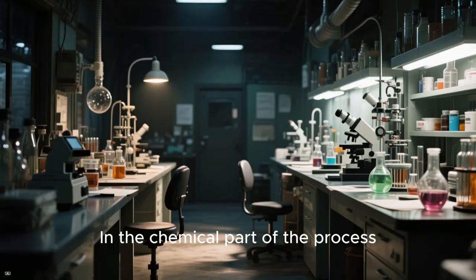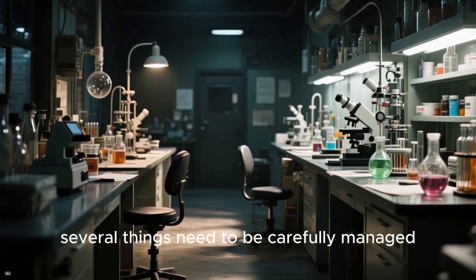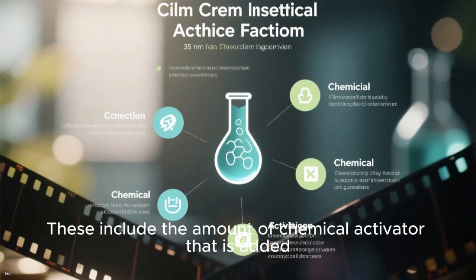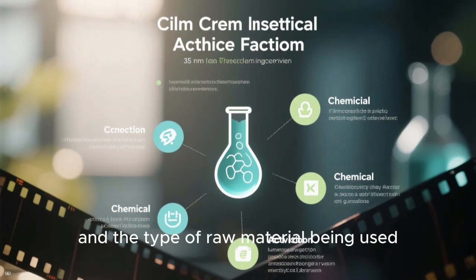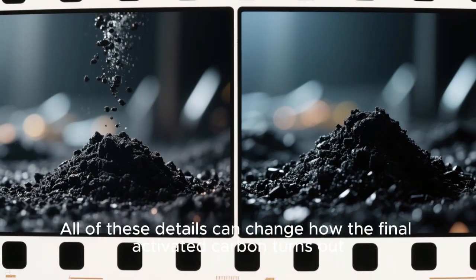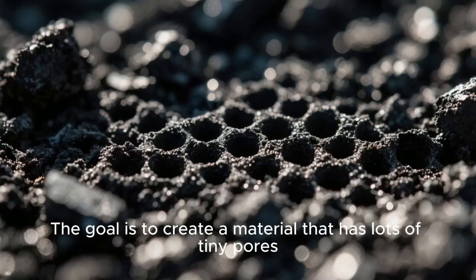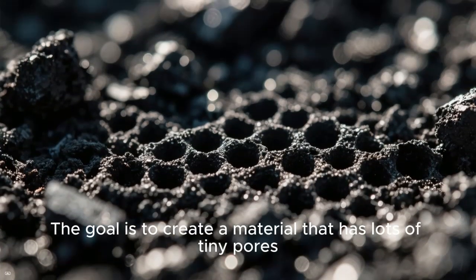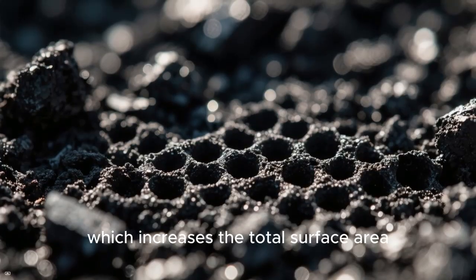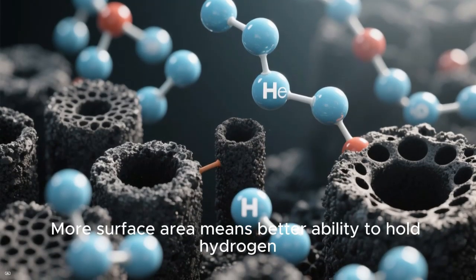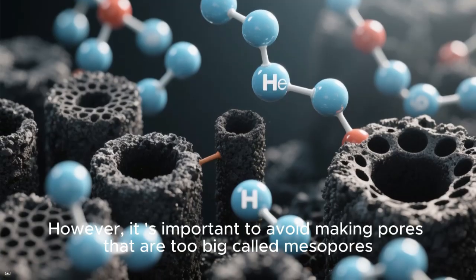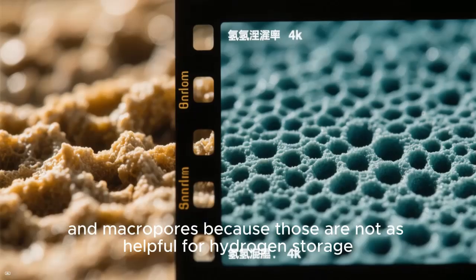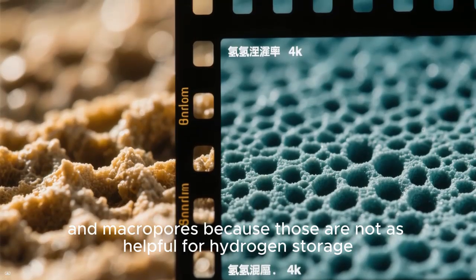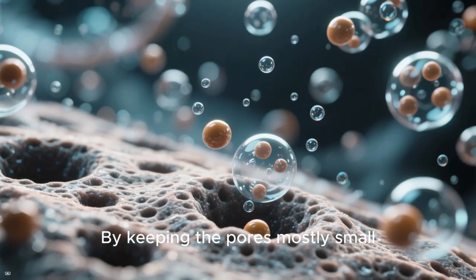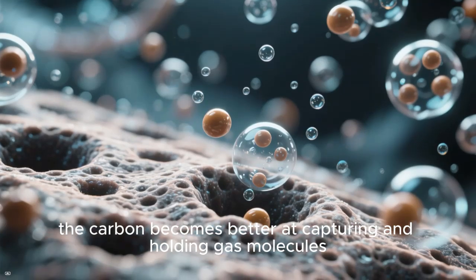In the chemical part of the process, several things need to be carefully managed. These include the amount of chemical activator that is added, how hot the process gets, how long the activation lasts, and the type of raw material being used. All of these details can change how the final activated carbon turns out. The goal is to create a material that has lots of tiny pores, which increases the total surface area. More surface area means better ability to hold hydrogen. However, it is important to avoid making pores that are too big, called mesopores and macropores, because those are not as helpful for hydrogen storage. By keeping the pores mostly small, the carbon becomes better at capturing and holding gas molecules.